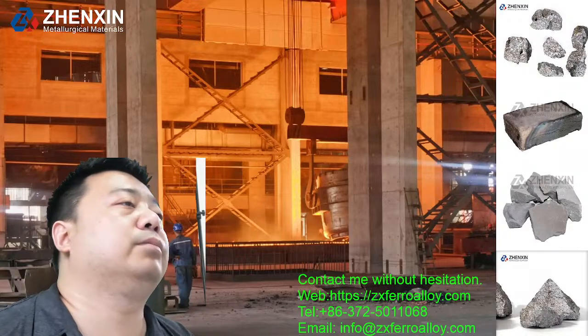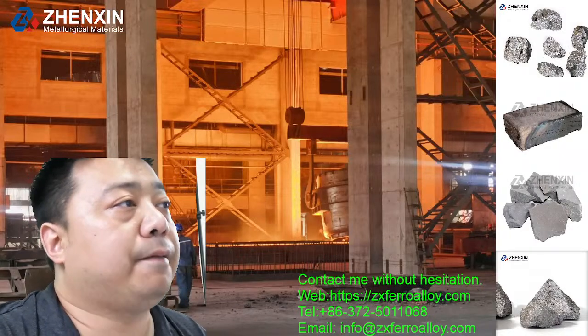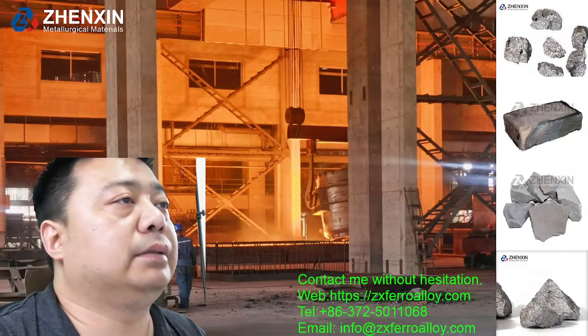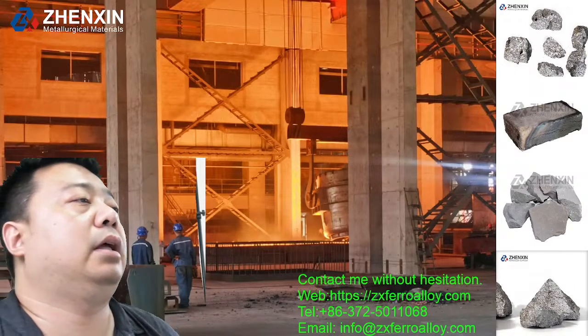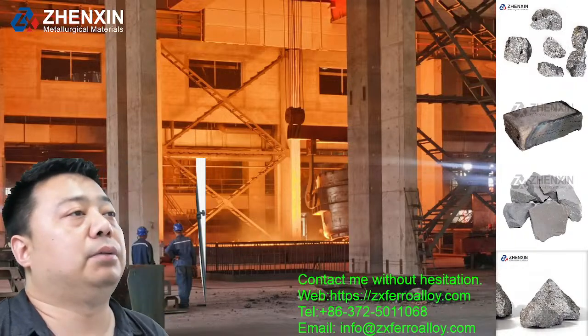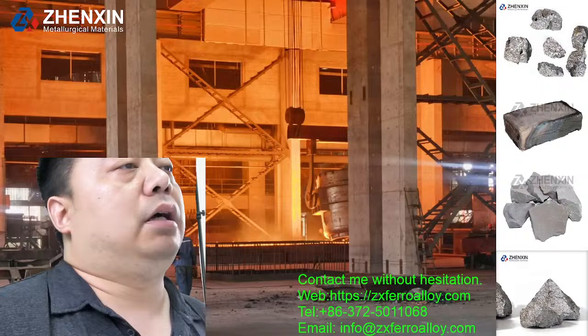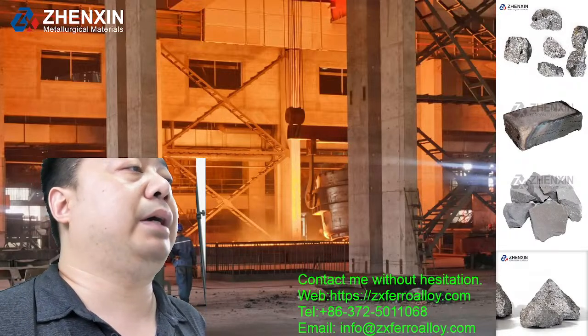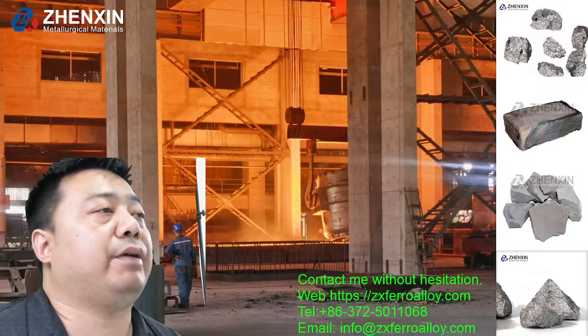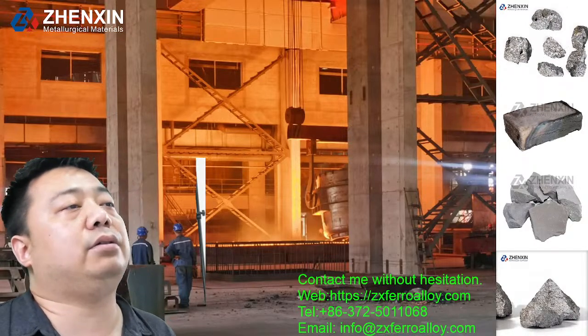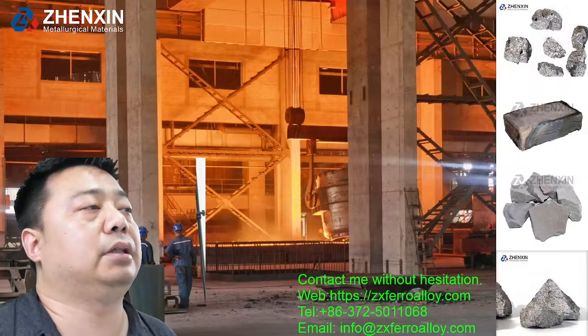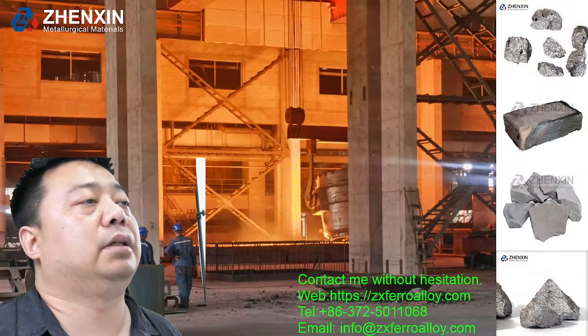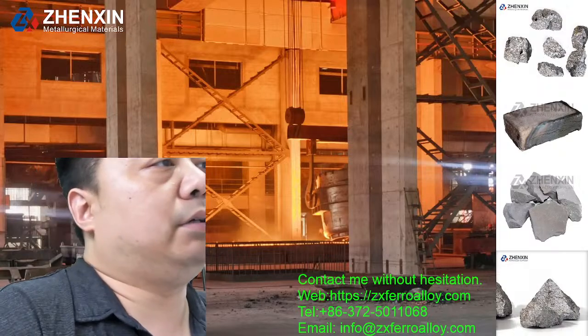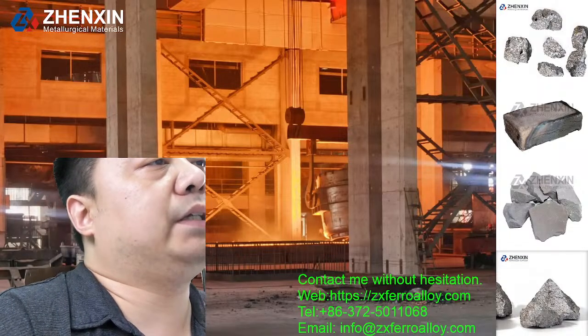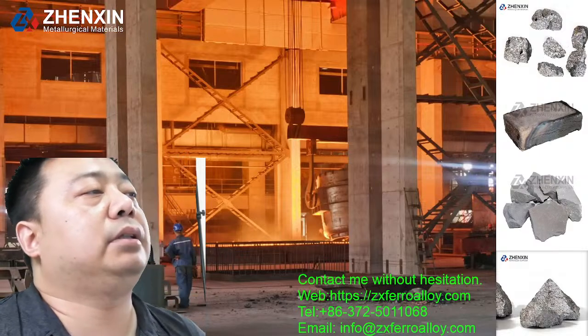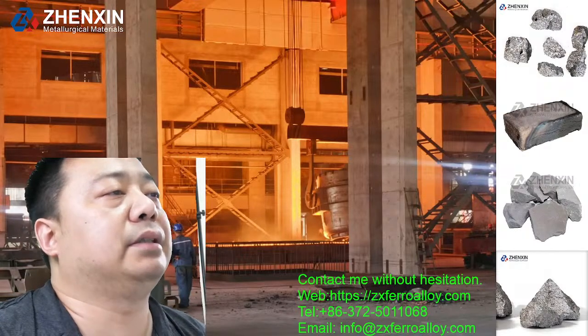Why do we choose the calcium iron cored wire? The invention of alloy cored wire is to solve the problem that alloy deoxidizers such as calcium cannot reach the deeper position of the molten steel to react. Although calcium is a strong deoxidizer, its relatively light specific gravity and low melting point make it easier to generate bubbles at high temperature. Therefore, simply throwing calcium metal particles or calcium powder into the refining furnace will quickly cause boiling and cannot enter the deeper position of the molten steel.